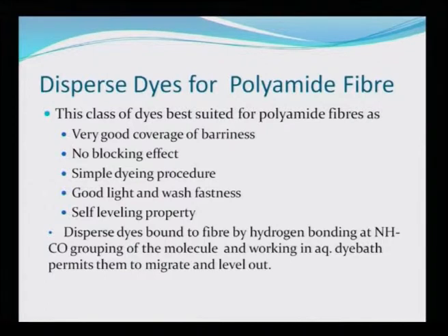Disperse dyes for polyamide fiber. This class of dyes, best suited for polyamide fiber, has very good coverage of barriness, no blocking effect, a simple dyeing procedure, good light and wash fastness, and self-leveling properties. Disperse dyes are bound to the fiber by hydrogen bonding at the NHCO grouping of the molecule, and working in an aqueous dye bath permits them to migrate and level out.